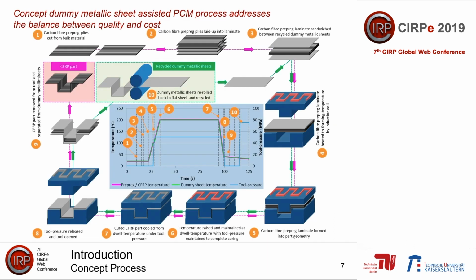So this is our concept part manufacturing process, which aims to address that balance between the sacrifice of part quality and the cost. We can consider this as a dummy metallic sheet assisted pre-preg compression molding process. So we start with our pre-preg material, lay up into the desired laminate configuration, sandwich between dummy metallic sheets, place in the forming tool, induction heat to the forming temperature, form into the part geometry, continue heating to the dwell temperature, then under the action of the heat and the tool pressure, we cure the pre-preg.